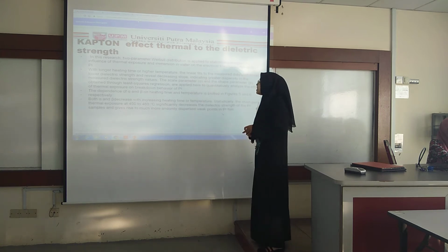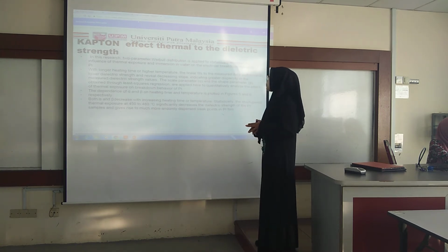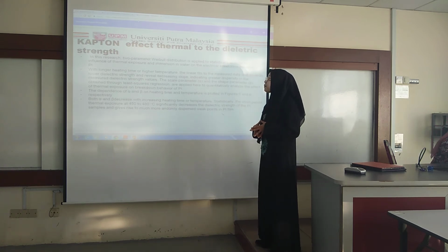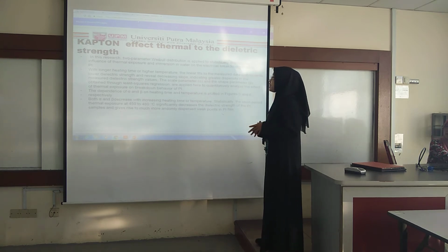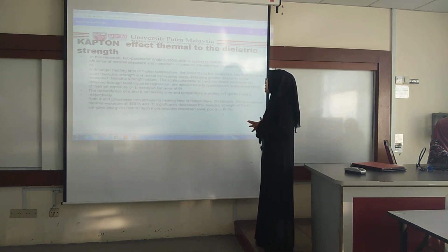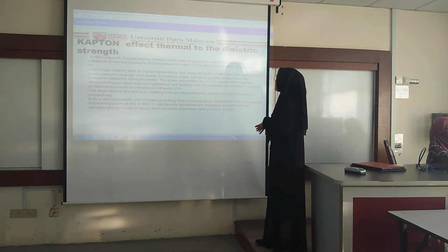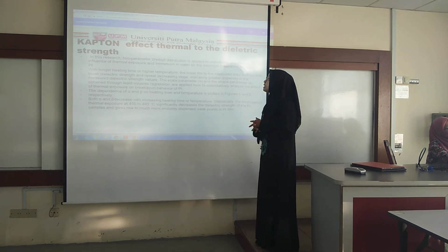In this research, a two-parameter Weibull distribution is applied to statistically analyze the influence of thermal exposure and immersion in water on the electrical breakdown behavior of PI. With longer heating time or higher temperature, the linear fit to the measured data shifts toward a lower dielectric range, and the decreasing slope indicates greater dispersity in the measured dielectric range values.